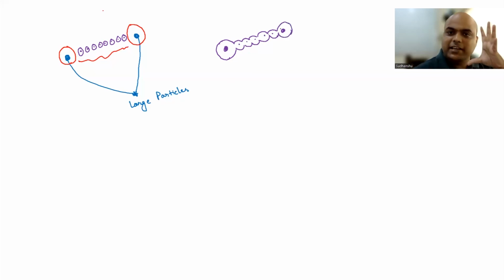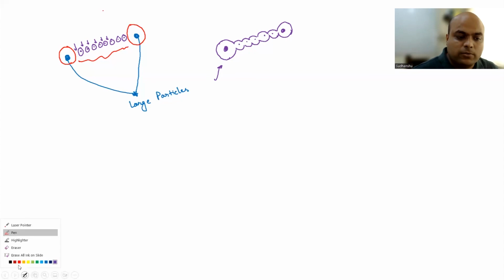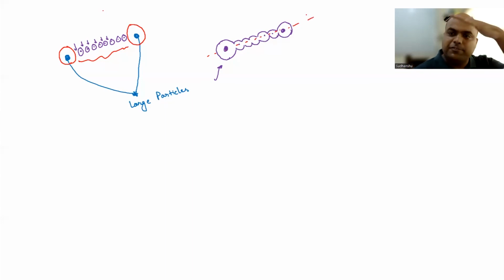That is very nice for understanding, right? Just assume that there is a micro tensile sample in all these regions. On the left side now I am drawing. And these are like, there are no particles, so they are pure, so they are going to rupture, right? So your final schematic is this, and it is going to now fail along this direction, right? So this is like your fracture plane. So you are going to again get the two fracture surfaces with lots of dimples. So these are your dimples on both fracture surfaces.